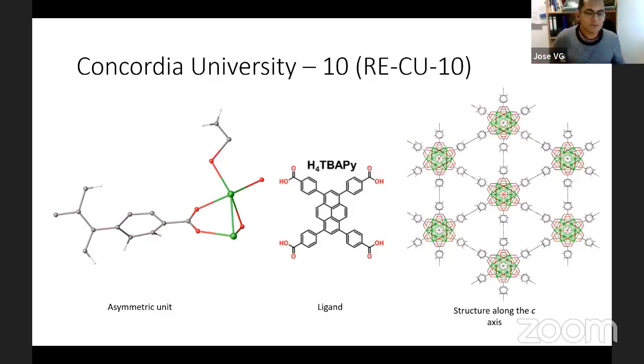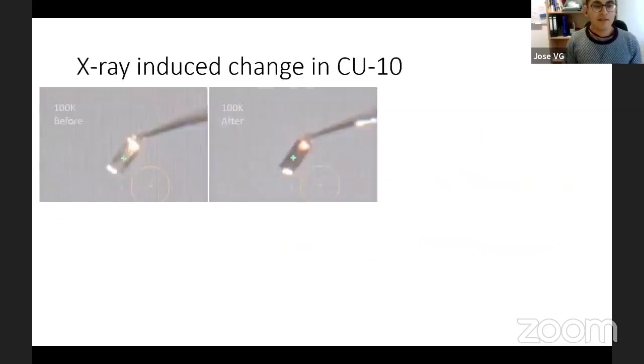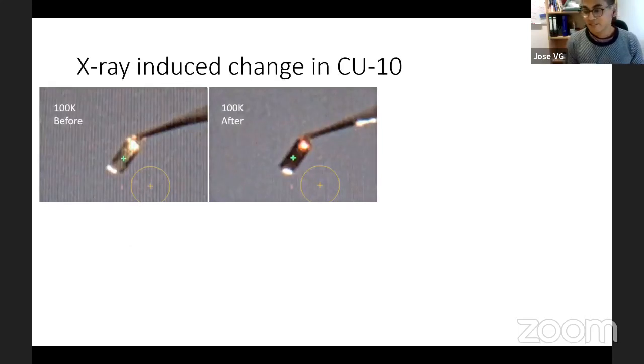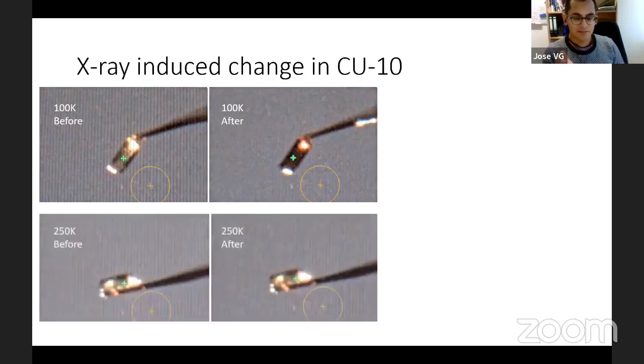However, when we tried to use the photocrystallographic technique, we had a problem. The material has an X-ray induced transition. As you see, the material changes at 100K from a yellow color to a red color. And that occurs at just some specific wavelengths of excitation with the X-ray, not at every excitation. And this occurs only at some specific temperatures.